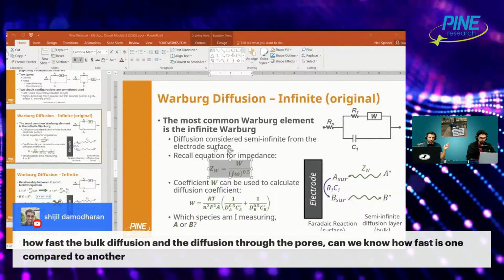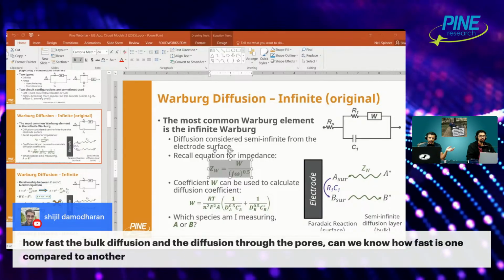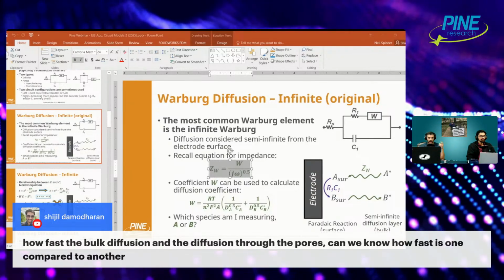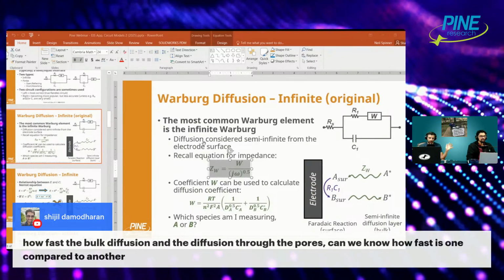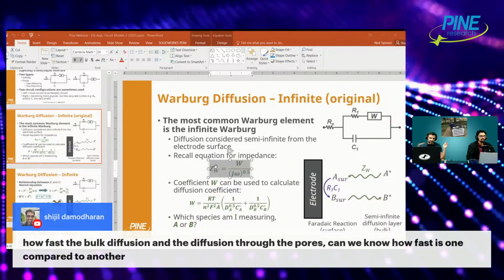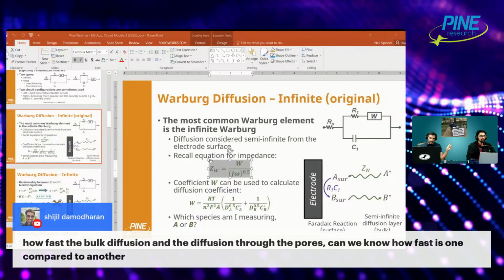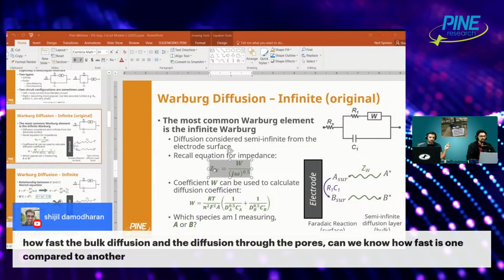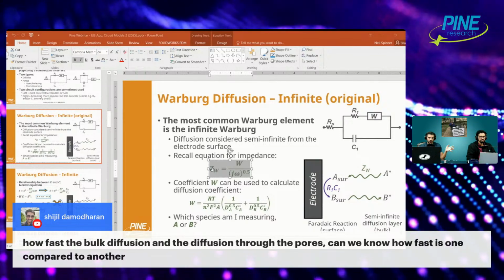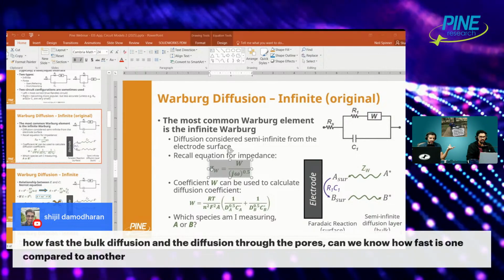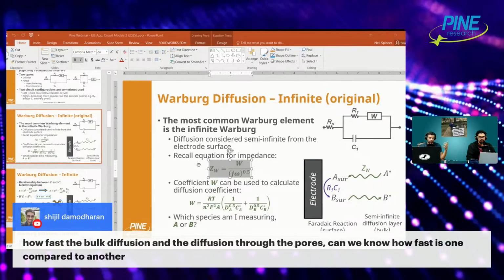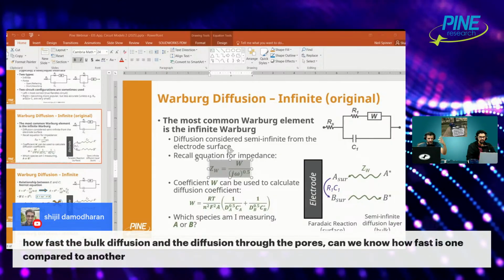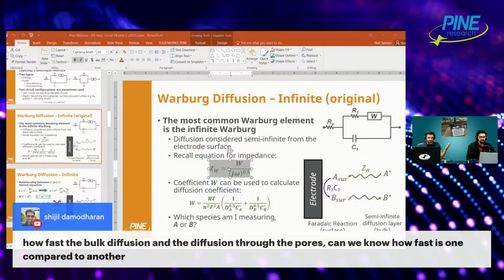If the Warburg impedance of material A is 1,000 ohms and the Warburg impedance of material B is 100 ohms, we would say that the diffusion is worse for A. It's higher impedance. Like V is IR, the higher the impedance, the lower the current I can get out of it. The worse its performance, so to speak, right?